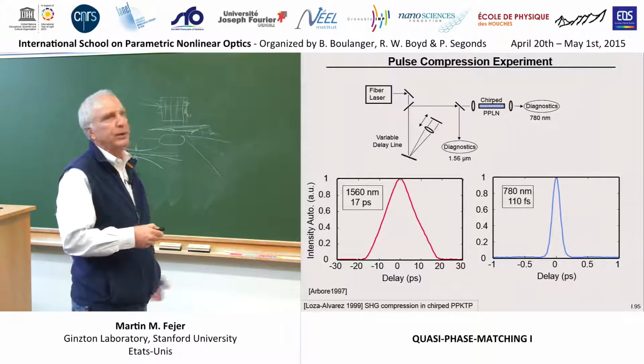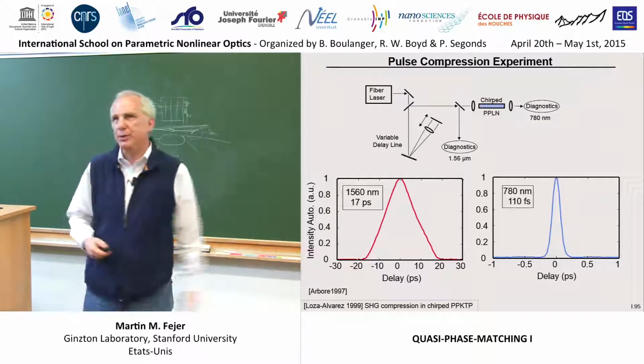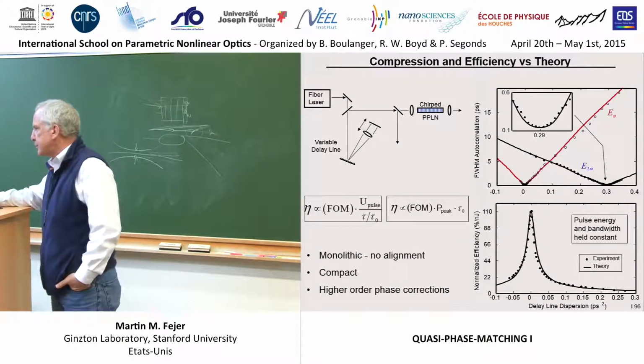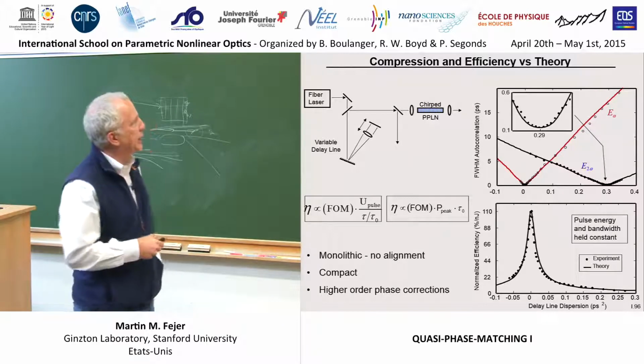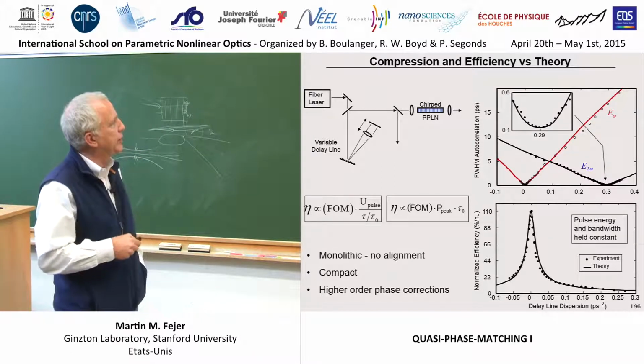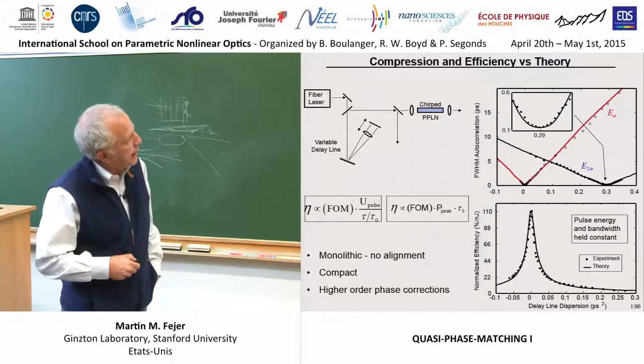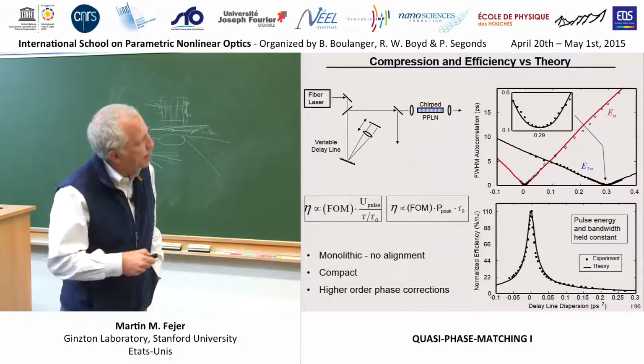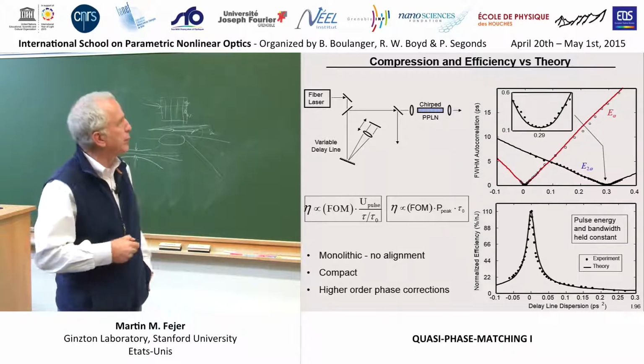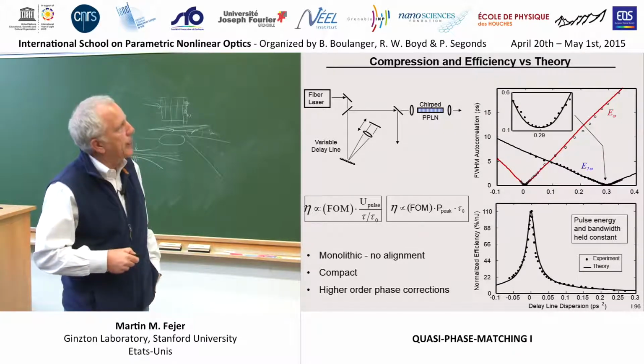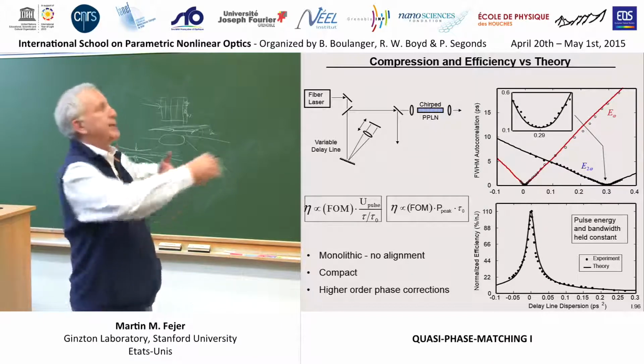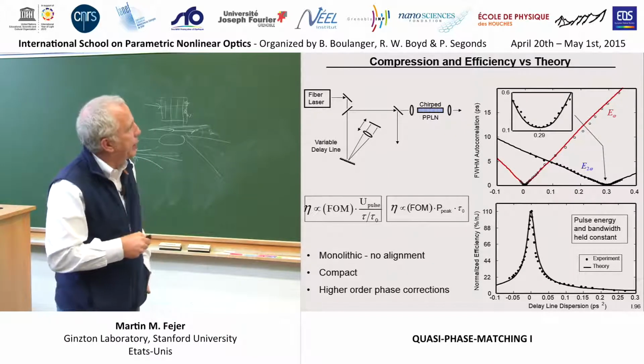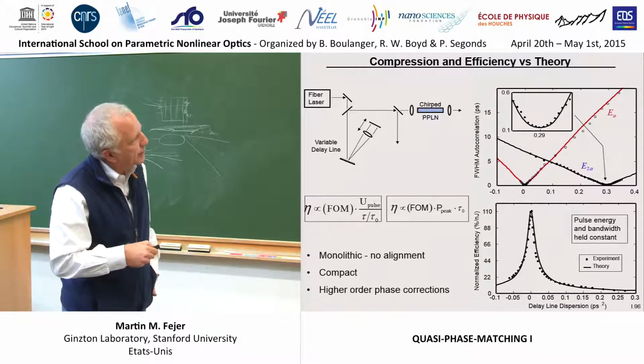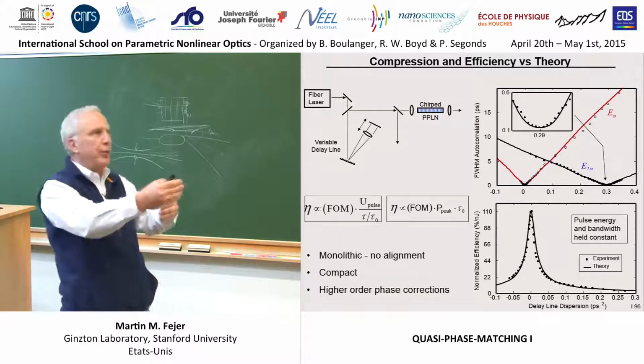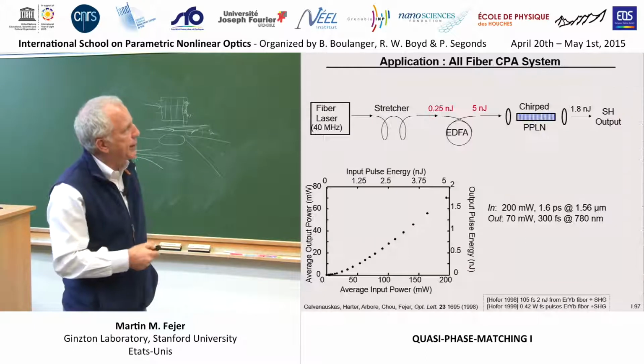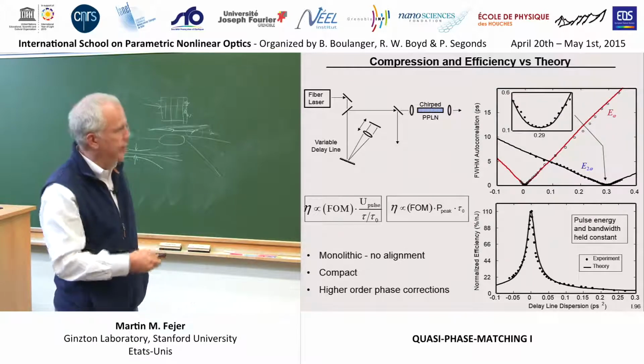So this thing did what that simple mathematical model said it was supposed to do. And in more complete detail, if you vary the amount of dispersion you add, group delay dispersion, the input pulse has a minimum duration when you have no additional dispersion here. But the second harmonic is rather long because it's added some dispersion now. But as you put in more and more dispersion on the pump, it's getting longer, but the harmonic is getting shorter because you're reaching the point of perfect compensation, and it exactly, again, follows the simple-minded theory we talked about.